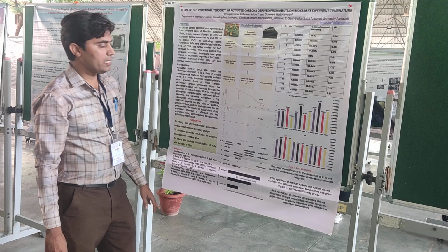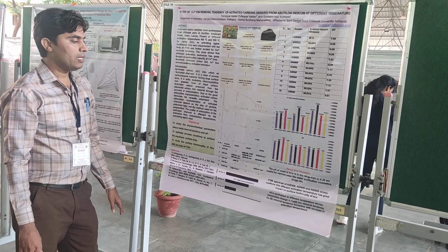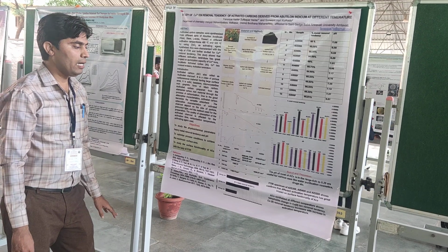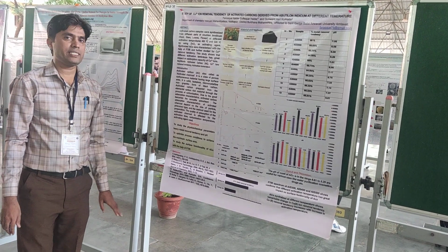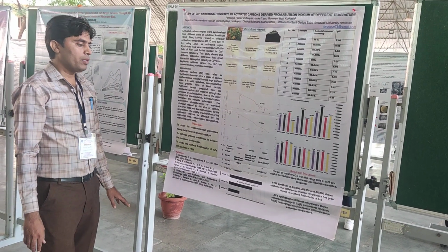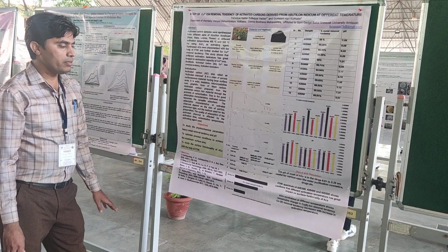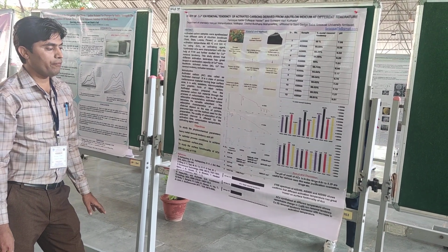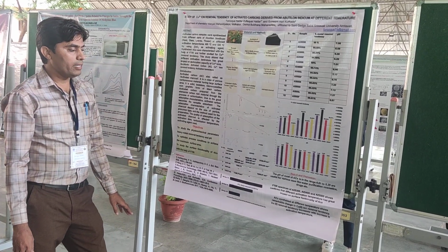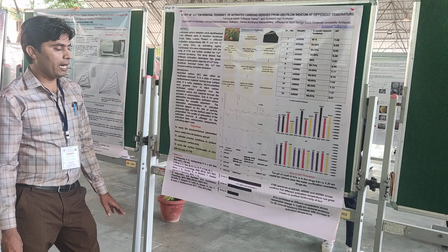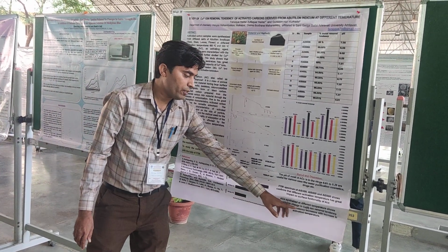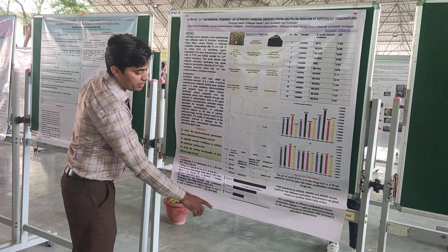This is the resultant discussion of my research. The pH of most of the activated carbons, in the range of 6.8 to 8.9, is useful for water purification, cosmetics and drugs. And the activated charcoal synthesized at different temperatures shows a remarkable change in the removal tendency of copper ion. As the temperature increases, the removal tendency of copper is also increased, which is shown here.